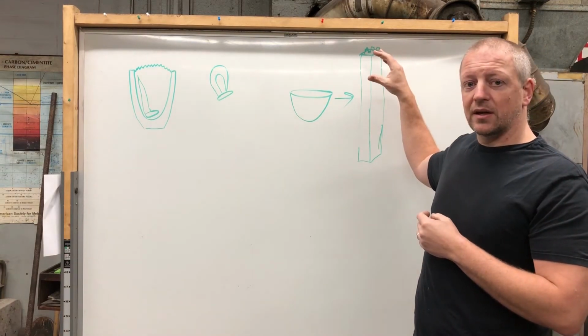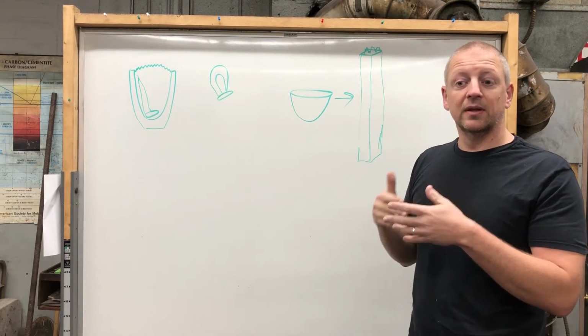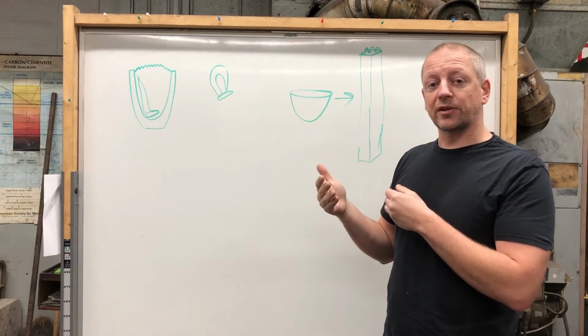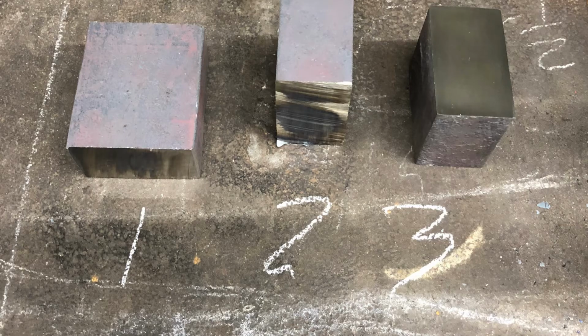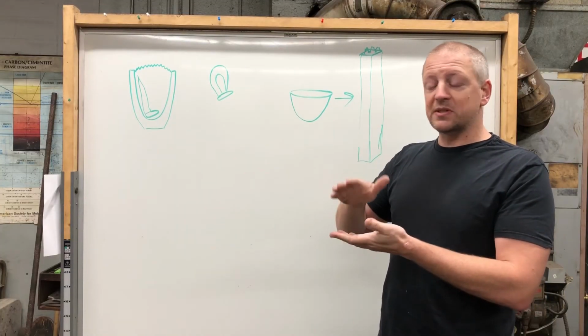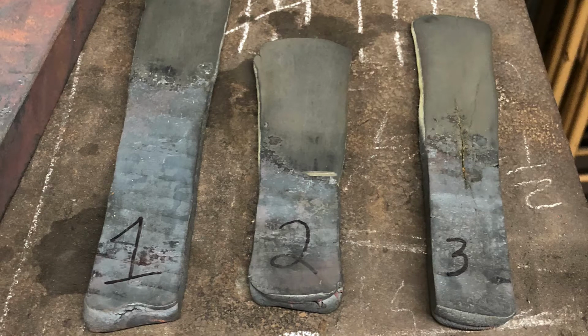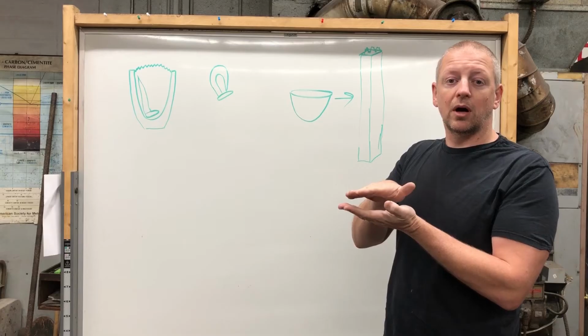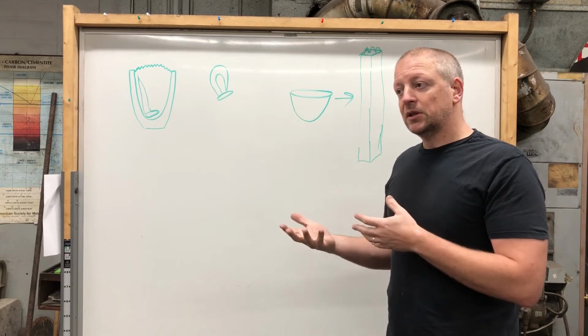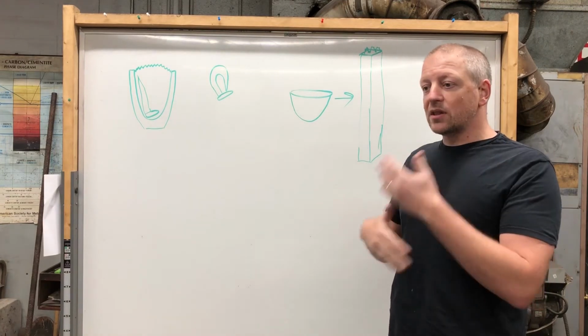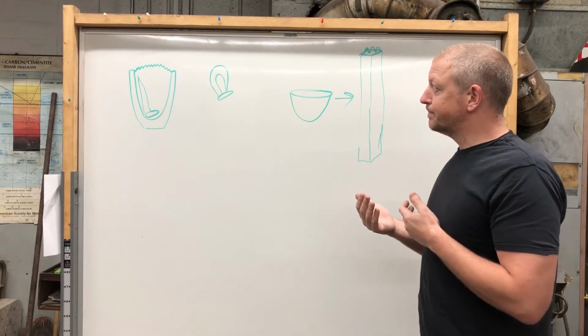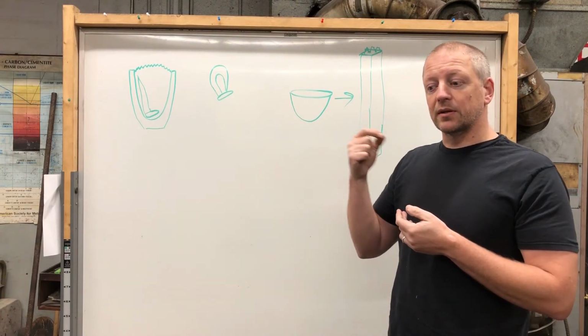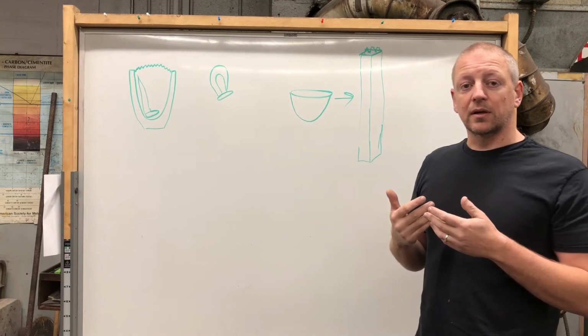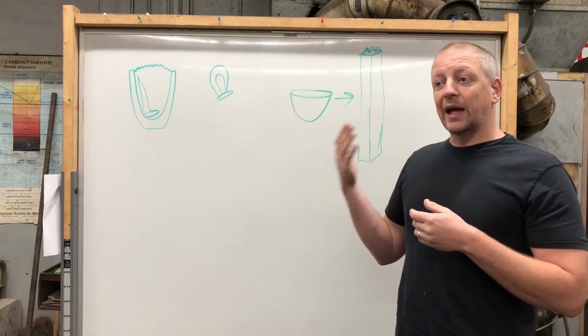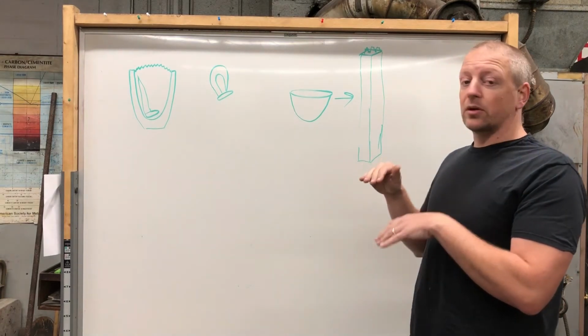Now, since I had trimmed off these pieces, I decided to have a little fun with, what does the pattern look like if I forge out in different directions? Again, got some stills showing the orientation of those bars, those little chunks. Basically, those pieces, I took them and flattened them out as though, in that picture, they were sitting on the anvil. I tried to forge them all essentially the same way, the same heat cycles, etc. They are not hardened, so the pattern you see is a little different than what I typically get in my blades. And intriguingly, two of them look almost identical.